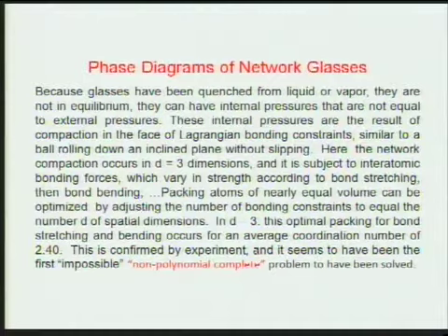So then I began to work on these phase diagrams, and the problem is there's a technical problem here. And the technical problem is that when you quench them, they don't, as I say, form nice crystals, and they're not really in equilibrium, but they're almost in equilibrium. They will stay in the quenched configuration for a very long time. For instance, window glass, if you just throw it out in the garbage and it doesn't get heated too much, it'll last, I have no idea how long, millions, jillions of years, and it's still not in equilibrium.